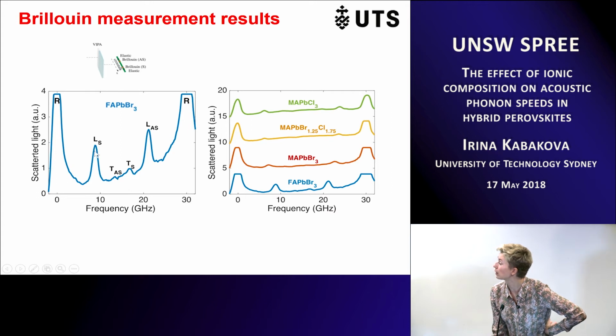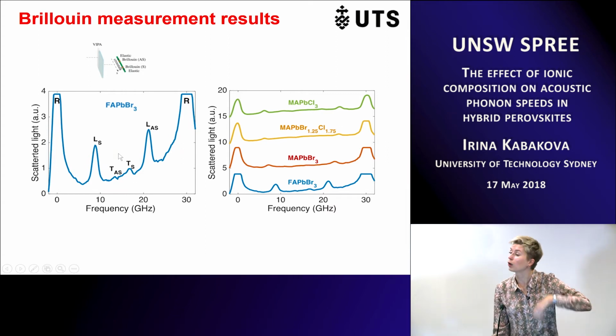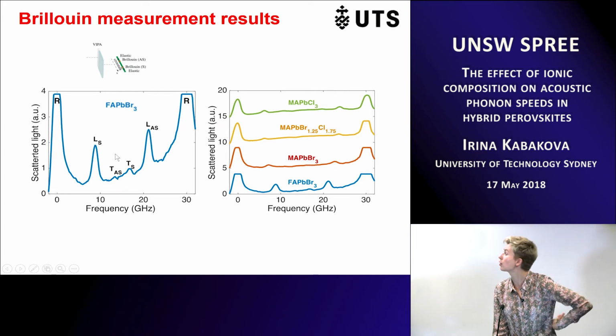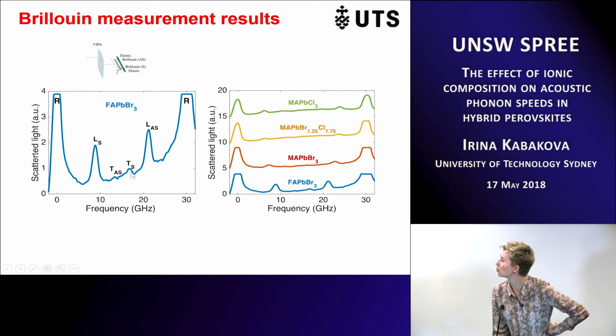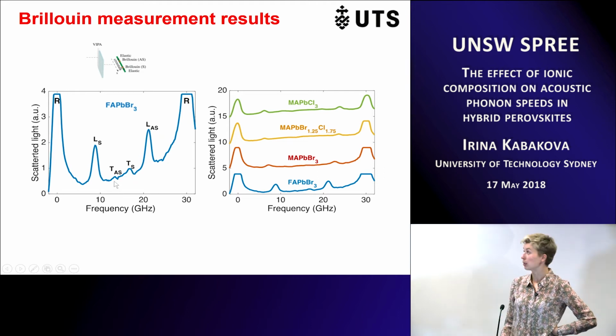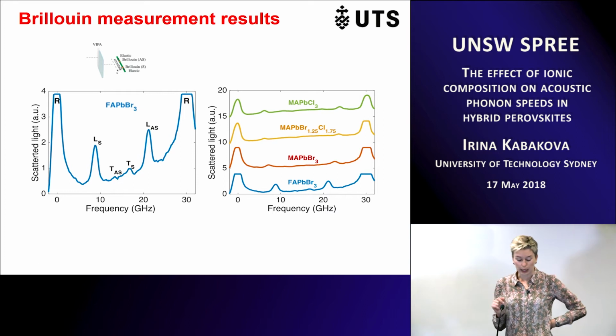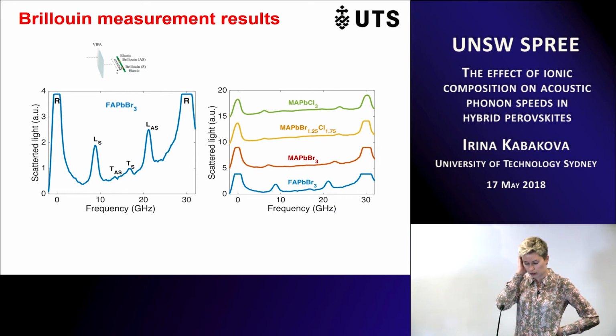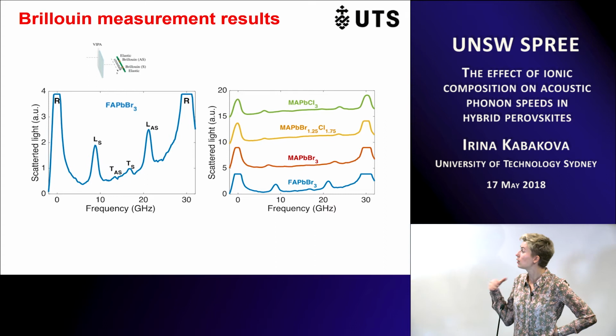So this, for instance, corresponds to a longitudinal acoustic wave, and it's the Stokes peak. So it corresponds to this high order diffraction, and Stokes are on the left-hand side because we lost the energy, and anti-Stokes are on the right-hand side, and we have also two little peaks for transverse acoustic waves. So analysis of this spectra takes a little bit of time and experience, but nonetheless it's fairly straightforward.